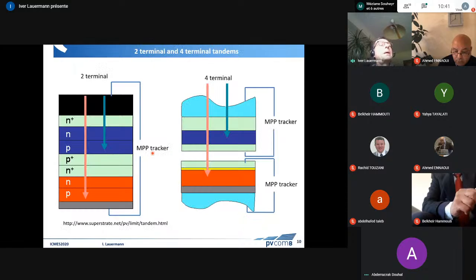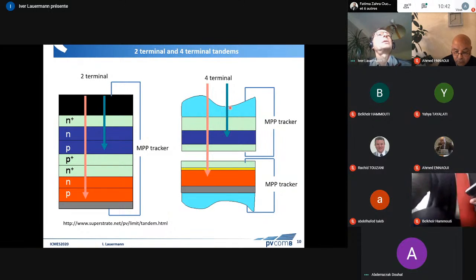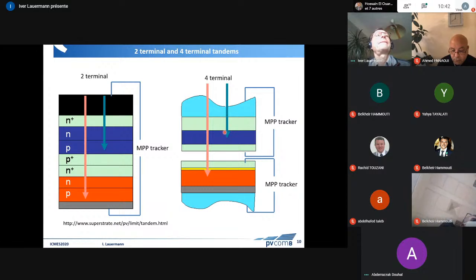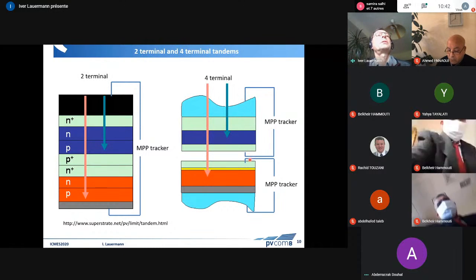Now, if we look at a tandem, there are several ways of combining materials. We can, for example, in a so-called 4-terminal device, simply stack them, mechanically stack 2 solar cells. The upper one with the larger band gap is partially transparent for the red light, for the long wavelength. And so it absorbs the high energy light, and the red light goes to the bottom cell, and both of them are individually connected to an MPP tracker, and we can utilize the power. Now, because here we have 4 terminals, this is called a 4-terminal or 4T tandem.